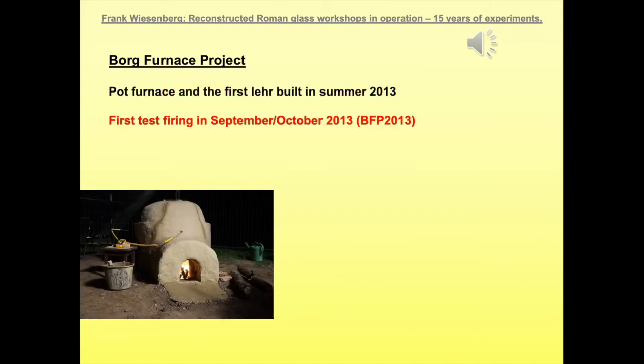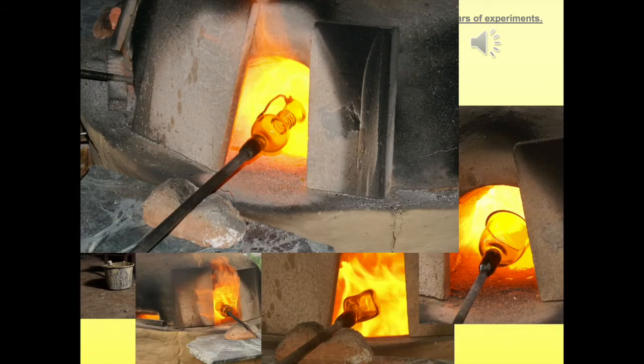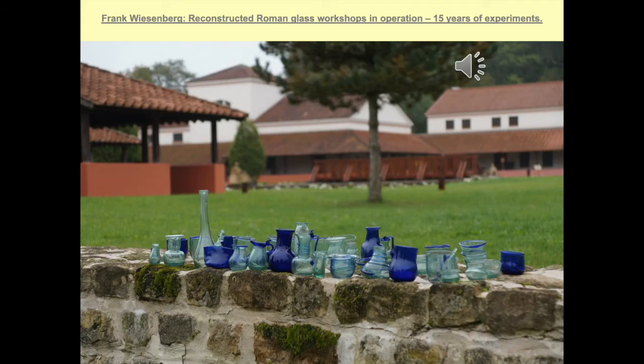During the test firing of the large pot furnace in Borg during September and October 2013, published as Borg Furnace Project 2013, we did a lot of temperature recording using the prepared holes, and we had to cover a lot of cracks from the still quite wet glass furnace dome. But even being not very practiced glassmakers, not being very artistic, we were able not only to melt glass, but also to blow a couple of vessels using the reconstructed glass furnace at Borg. Not only the glass furnace, but also the annealing oven worked very, very well at Borg.